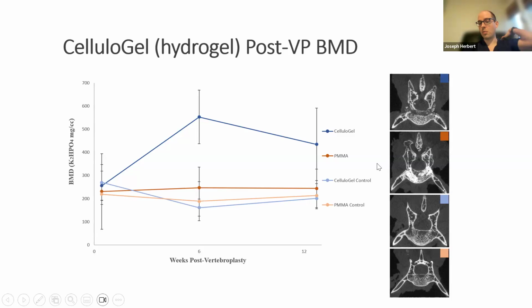So potentially, maybe this has something to do with that controlled release of ions that we're saying. Again, the initial use of these chitosan hydrogels in this lab was actually for drug delivery. And so this is a rethinking of vertebroplasty in a lot of ways, because this compound, when it gelates, has very similar mechanical characteristics to osteoporotic bone, but it's also constantly releasing these phosphate and calcium ions into the surrounding bone tissue. So it's both a structural additive to the spine in the same way that PMMA is, but it's also taking an active role in the bone biology, unlike the inert nature of PMMA.